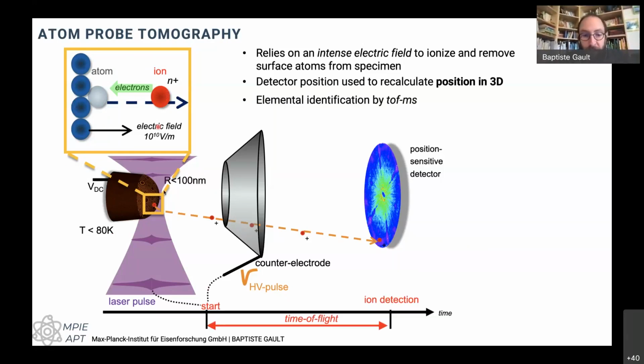So knowing when the ion is created, and we can also look at when it lands on the detector, we can actually measure the time of flight of each ion. And you can imagine that if something is a big fella like tungsten, it will just travel quite slowly. If it's tungsten bearing more than one charge, like 2, 3, 4, it has lost 3 or 4 electrons, it's going to be accelerated a bit more. But then if you're looking at something like carbon that is really light, it will just travel much faster. So there is a direct proportionality between the time of flight of an ion and its mass to charge ratio. So we can directly use this information to identify which element was each of the ions that we've detected.